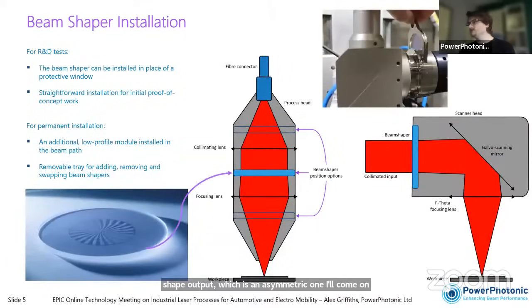In terms of how you install these into a practical system, for R&D trials, we've had some good results so far by replacing a protective window with one of our optics. So these process heads will typically have at least one protective window somewhere in the system. We can remove that, replace it directly with an optic of the same geometry to generate the beam shape at the output. This is good for a quick test. Might not be practical for a full manufacturing system. These really aren't sacrificial components, and you don't want to treat them as such.